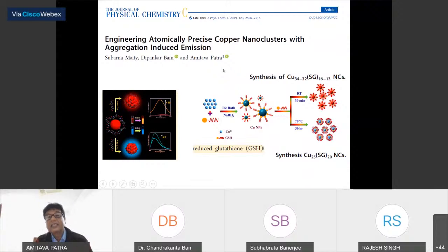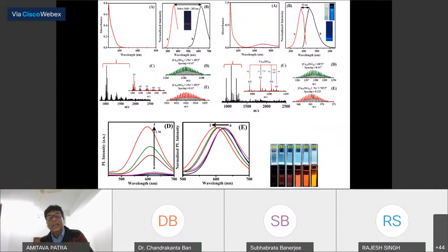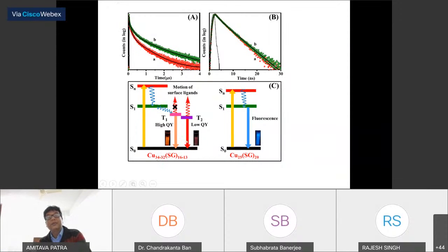This is green emission by HOMO-LUMO, and it is excitation independent, so there is no defect structure over there. Another important cluster, which we published last year, is on another important topic, aggregation induced emission. Here are copper 34 clusters and copper 25 clusters, with the number of atoms, and we have done all these characterizations. In the case of the copper 34 cluster, we have seen aggregated emission. That is, you can enhance the emission property in the presence of solvent. But in the case of copper 25, there is only blue emission. In copper 34 or 32, it is a red emission. So you can tune the emission from blue to red, and you can enhance the quantum yield by using this molecule, by changing the number of atoms.